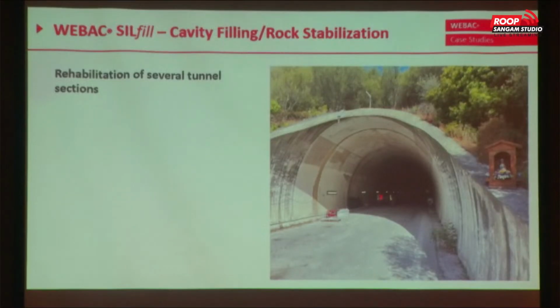So coming back to the job site in Italy, that was a rehabilitation of several tunnel sections. You see one of these tunnels here, and it looks nice, bright and shiny in front of it, but we entered it, and the case here why we had to use silicate foam resin was they did some core drillings, and they figured out some big, wide, huge cavities on the ceiling of the old tunnels. First the decision was, okay, using a cement, of course, but the thickness of the concrete wasn't so thick in the back or in the middle of the tunnel. That means if you inject a lot of cementitious grouting, you have a lot of load which comes to that point. Therefore we decided, okay, let's move to a silicate foam resin, which is a lightweight cavity filler, and also stable enough to protect the rock or the gravel from falling down.